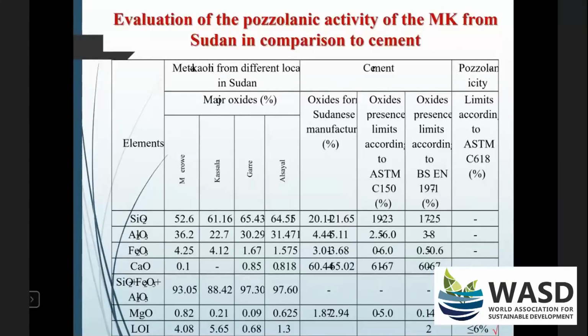As for the obtained samples of the metakaolin, we had to check the chemical composition of the material by determining the oxides present in our samples. So we were focusing on the major oxides because we're trying to compare that to ordinary Portland cement. The samples were obtained from 4 different locations in Sudan, Marawi, Kassala, Garri, As-Sayyal, and we had the analysis, and then that was compared to the major oxides considering 3 different standards: the Sudanese manufacturers and the limits according to the ASTM, as well as the limits according to the British standard.